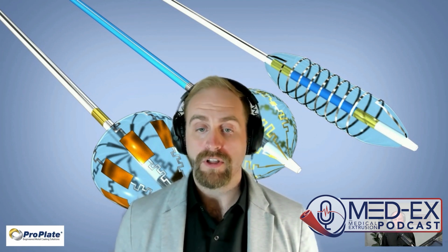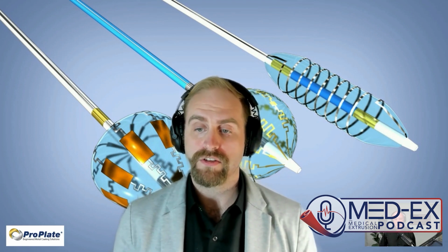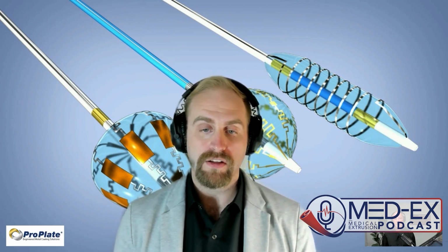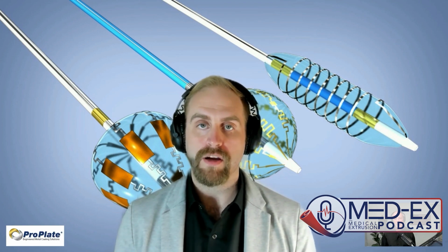But then there's cycle testing that we'll collaborate on with our customers that can cycle the balloon, inflate it, and expand it, stretch it, manipulate it, and then also test for adhesion in the same way afterwards. And then corrosion testing, we are using inert materials for this process, so we're not really concerned about that, but it always comes up, whether it be galvanic corrosion or just corrosion in general, where customers have those concerns. And so we can do accelerated saline soaks, which we have done, to prove that the metals will not corrode even in a saline environment over time at an elevated temperature.